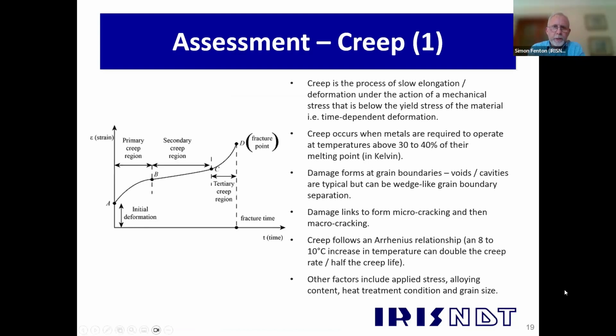So yeah, as Pete said already, probably the most common application of the acetate replica in the power industry is to monitor for creep damage. And just to give you an indication of the scale of the replica exercises that we undertake, if we embark on an outage, a statutory outage for a gas-fired site in the UK that has pipe work in the creep range, we could be taking up to 1,000 replicas or more during a 3 to 4 week period. So it's quite labour intensive. We have a team of replicators to do that, and obviously people looking down the microscope. So it's a replication on an industrial scale, really.